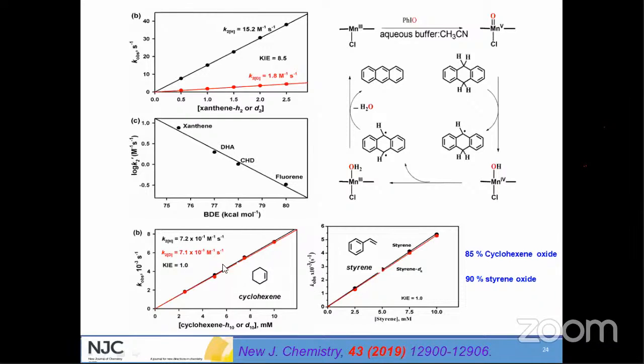Then further, we did the reaction with cyclohexene, taking deuterated as well as hydrogen containing substrate. When we did that, we got a different sort of reactant. The KIE value was 1. And when the KIE value is 1, this is straightforward evidence for epoxidation reaction taking place, right? So in other words, the hydrogen atom abstraction did not take place in cyclohexene, although it is possible, unlike with other metal oxide species. So to test whether it is really going through epoxidation, we tested.